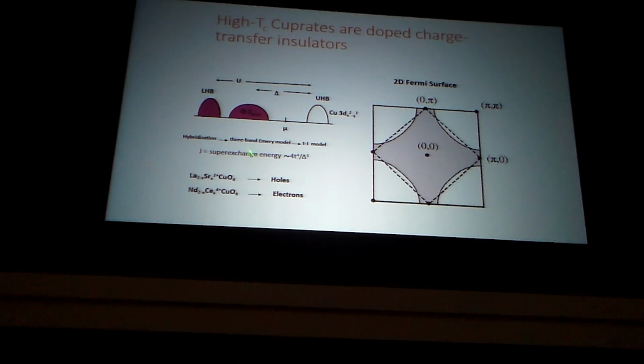That's just because the electrons or the dopants are actually in the oxygen orbital and not in the d orbital. And the energy gap is this charge transfer energy, not the Coulomb energy, which is called U. But there are various models to this that I'm not going to go into. And to dope it, if you want to put holes into the system, you dope with strontium. If you want to put electrons in, you dope with cerium. I'm going to talk mostly about what happens when you put electrons in.